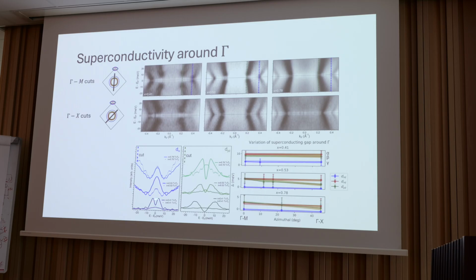And so what we see is that we can resolve a gap on this XY band at 41%, that closes above TC, as expected, but when we increase to 53%, which is still below the Lifshitz transition, we can no longer resolve a gap on that band, which is a bit surprising because maybe we expect the same bands to participate in pairing below the Lifshitz transition. Whereas for the YZ bands, we're able to see a gap on all 3 hole doping levels that stays open.